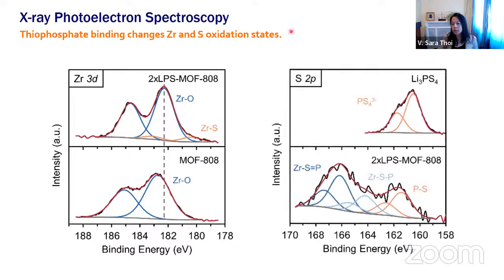If we look at the sulfur XPS, we do see some similar pictures. We indeed get one environment of our thiophosphate material outside of the MOF, whereas we get multiple environments of our sulfur once it's incorporated into the MOF, suggesting that we are indeed changing the identity of the thiophosphate and its local environment.